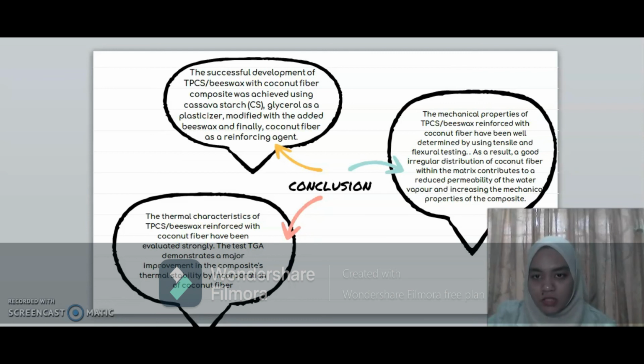And Objective 3. The mechanical properties of TPCS and beeswax reinforced with coconut fiber have been well determined by using tensile and flexural testing. As a result, a good distribution of coconut fiber within the matrix contributes to reduced permeability of water vapor and increased mechanical properties of the composite.